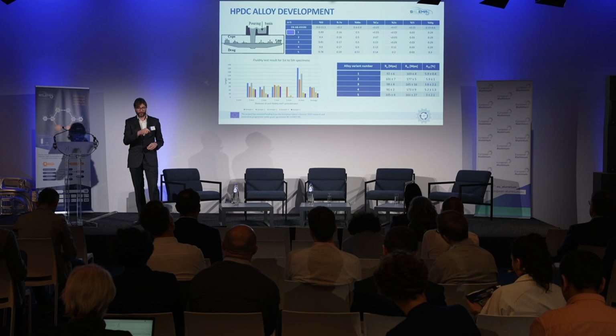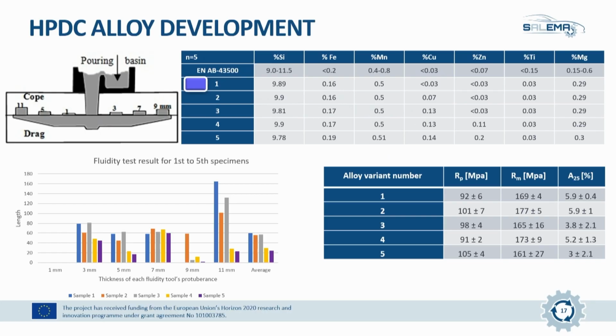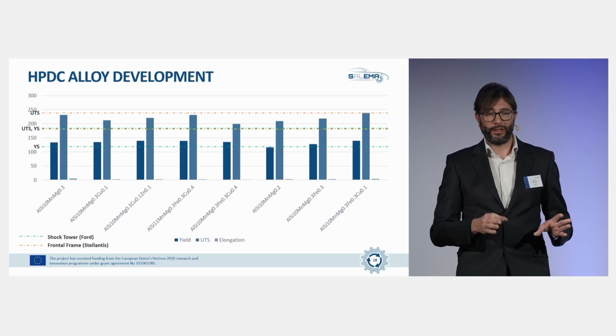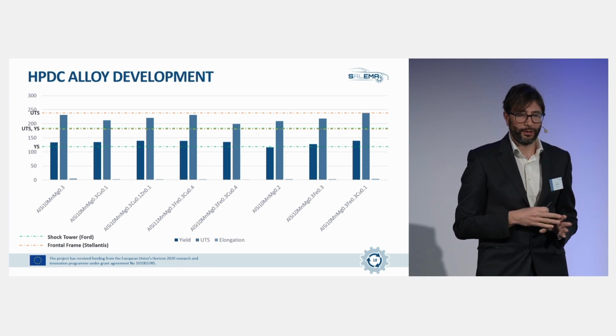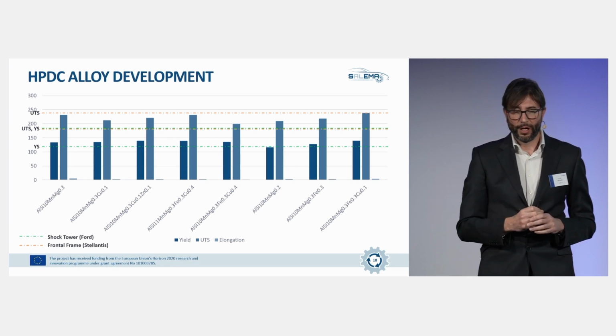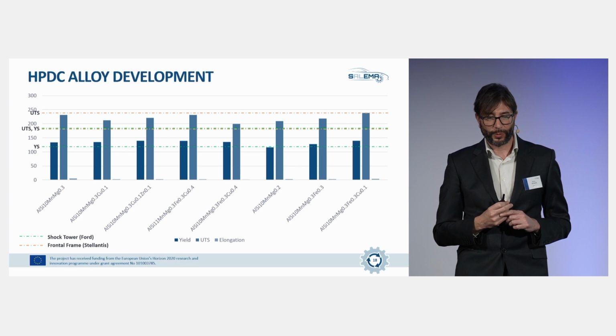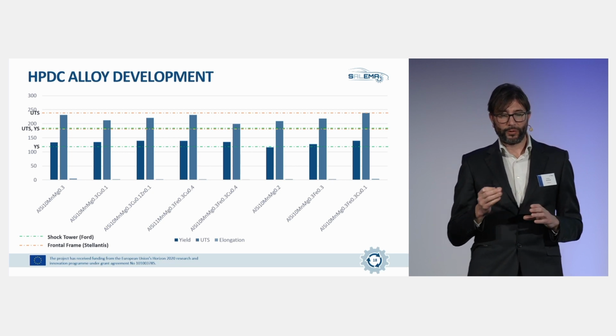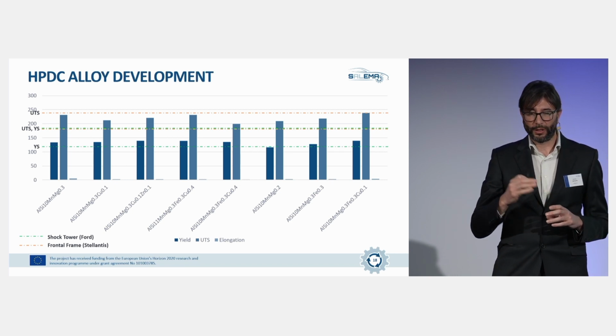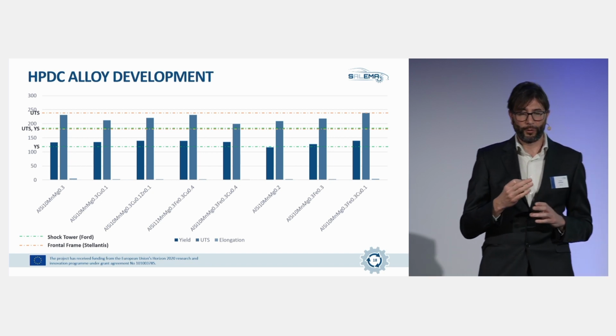Okay. Here, for instance, we can see that zinc, a small increment in zinc, decreased the alloy flowability quite a lot. And also we check the mechanical properties on the plates produced by gravity casting, but well, they are not representative of high pressure casting. From that, we select the most interesting alloy variants. Actually, we test 8 different alloy variants, using our high pressure casting machine at Eurecat to produce a 3 millimeter plate, where we measure the mechanical properties in the cast condition. And we found that already in the cast condition, most of the alloy variants met the requirements in terms of yield strength and ultimate tensile strength of one of the demonstrators, the shock tower.